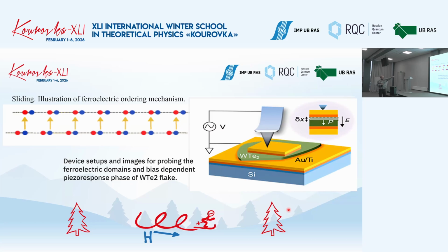Look, say we have these two layers consisting of red and blue atoms. And then we start to shift the positions of these lattices in different layers. It's an indication that you have some breakdown of symmetry, and you can have this dipole moment. Then you should calculate some distribution of electronic density and get it. And of course, I will not go into details of these complicated calculations, but believe me that people did it, and they illustrate the possibility to realize this sliding ferroelectric behavior.